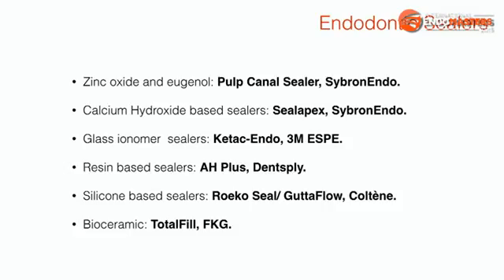Bioceramic sealers. The bioceramic sealers are composed of zirconium oxide, calcium silicates, calcium phosphate monobasic, calcium hydroxide, and various fillings and thickening agents. The material is available in a premixed syringe with calibrated intracanal tips. It is a hydrophilic sealer, and it utilizes moisture from within the canal walls to complete the setting reaction, and it does not shrink upon setting.